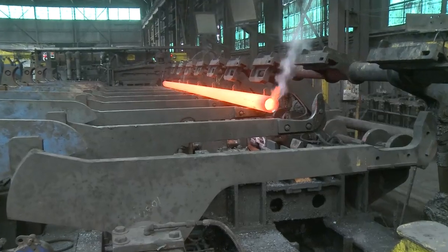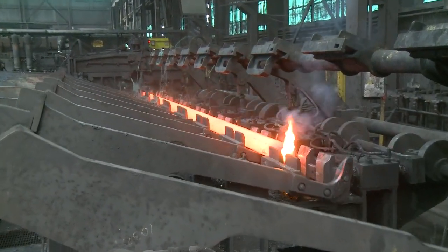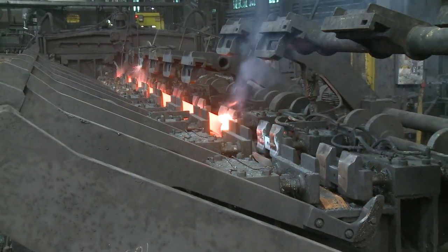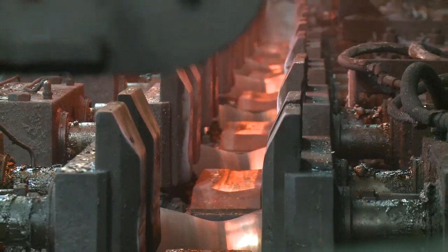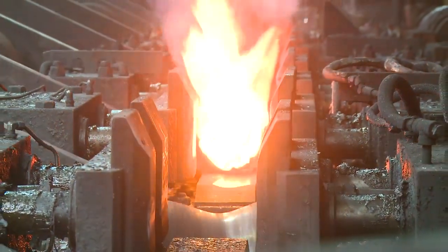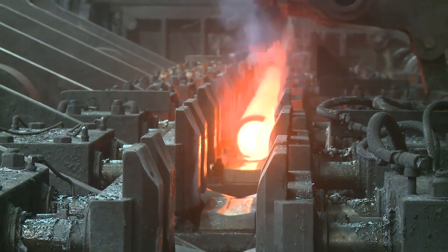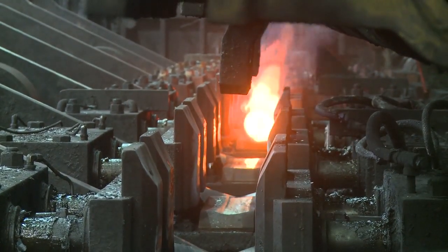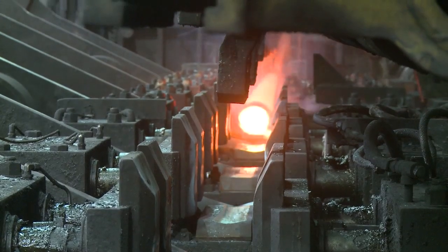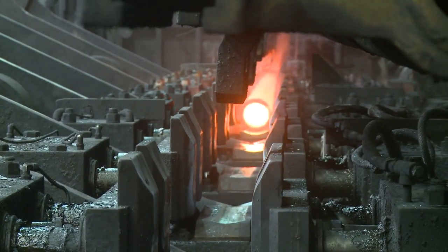Coming out of the reducing mill, there is a slight oval shape to the tube's dimension. We reduce this shape through a rotary sizer. This rotary sizer rounds the tube to a complete finished size. Since there is no internal support to the hollow tube, the rotary sizer uses minimal force to avoid damaging the tube.